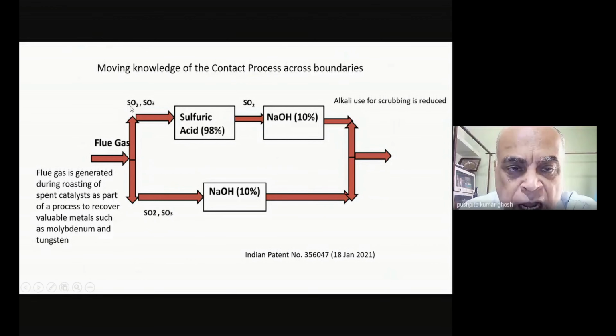And because I was a consultant for them, they had raised this issue that they were spending too much money to scrub out these SO2 and SO3. And they were using at that time sodium hydroxide solution and passing the flue gas through it. And basically, this stuff would come out. And also, of course, flue gas will have carbon dioxide. So it will form sodium sulfite, sodium sulfate, and sodium carbonate. But as more and more SO2 comes, the sodium carbonate will gradually get all converted into sodium sulfate or sodium sulfite, and the CO2 will subsequently escape.